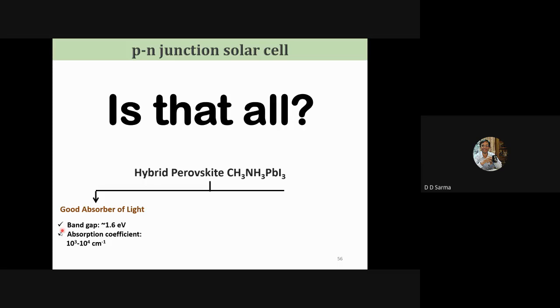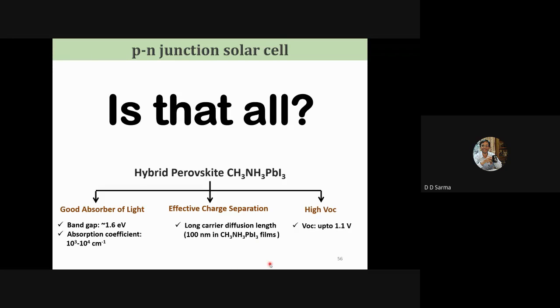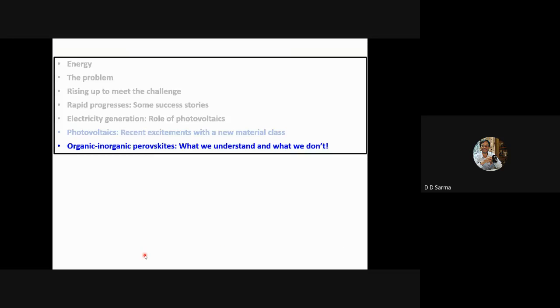And also it absorbs very rapidly. A very thin material is needed to absorb completely all the solar radiation. Not only that, after it has absorbed and created the electron and hole, this electron and hole has a very long diffusion length because I need to separate them. Within hundreds of nanometers in this film, they can get separated, which is wonderful, and that is required. And since it has a large band gap, it also gives me a large open circuit voltage, and so I get more energy. So these are all very good things.